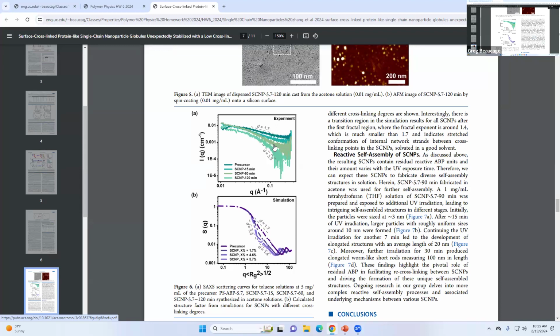Ones that have a rough surface, the dimension goes up, meaning that depending on the size scale you look at, it has more and more surface area. So 6 minus this 3.3 gives you 2.7, the surface fractal dimension. If it was 2, 6 minus 2 would give you 4, which is a smooth surface. So this is a rough surface.